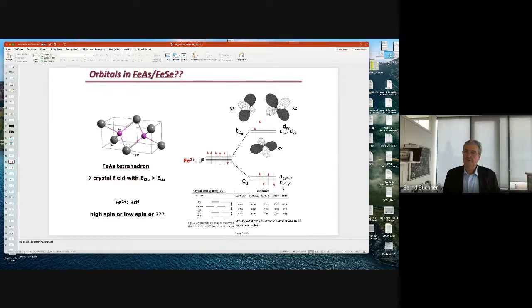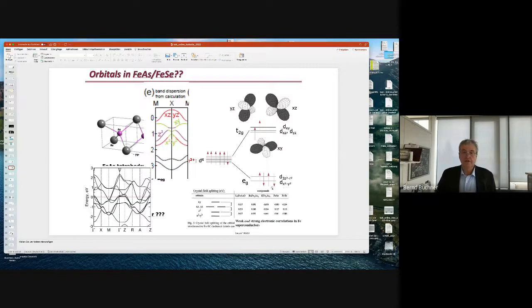Of course, this would be the case if we have a localized picture. Then we probably would end up with a high spin state. Now we know that we are not dealing with this completely localized thing. We are dealing with this band structure. And indeed, it turns out that the renormalized bands which we have still have an orbital character. But it's not so simple that there's one band which is clearly one orbital. They are intermixing and so on.